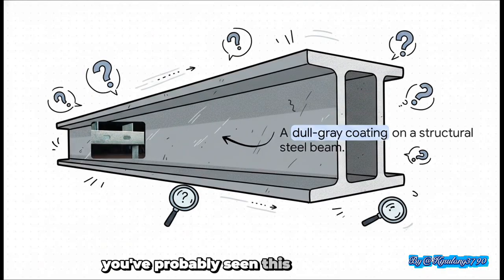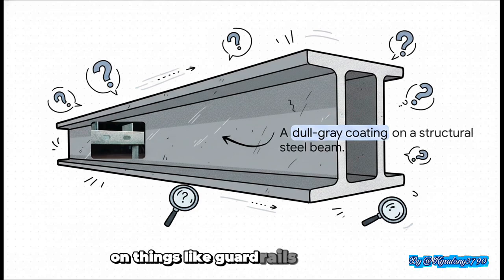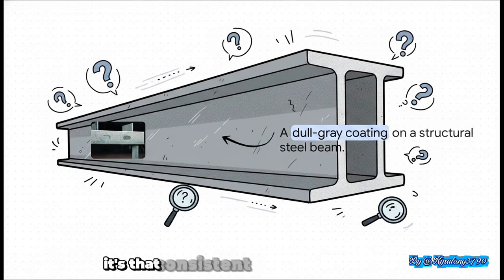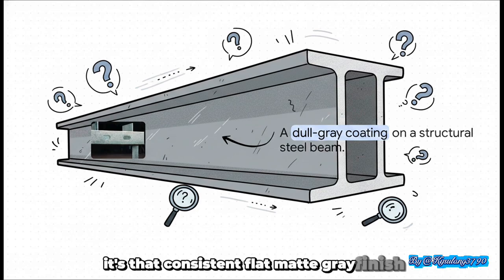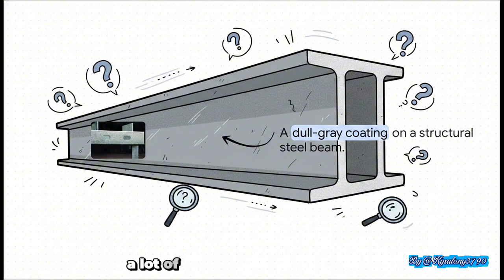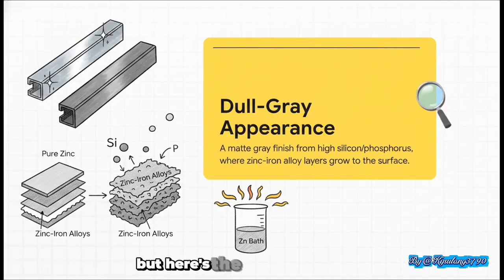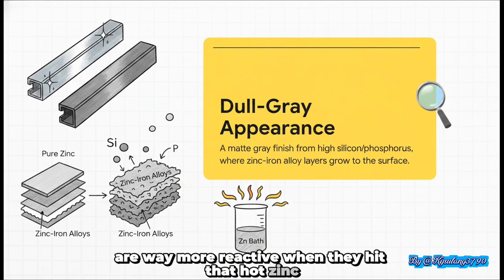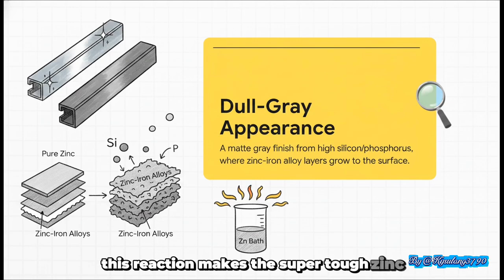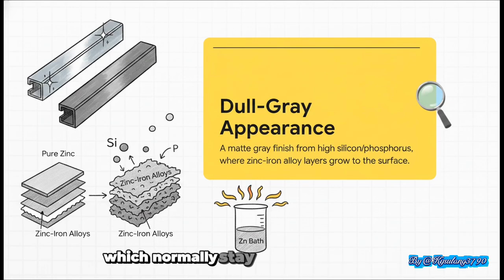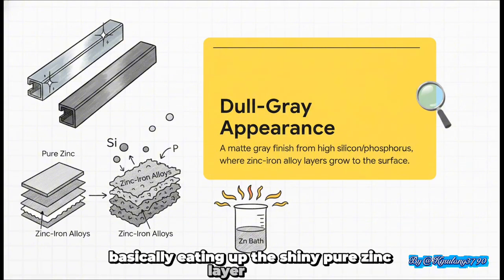You've probably seen this a million times on things like guardrails or structural beams. It's that consistent, flat, matte gray finish. And because it's not shiny, a lot of people look at it and think, uh-oh, something's wrong here. But here's the science behind it. Steels that have a bit more silicon in them are way more reactive when they hit that hot zinc. This reaction makes the super tough zinc-iron alloy layers, which normally stay hidden deep inside the coating, grow all the way out to the surface, basically eating up the shiny, pure zinc layer on top.